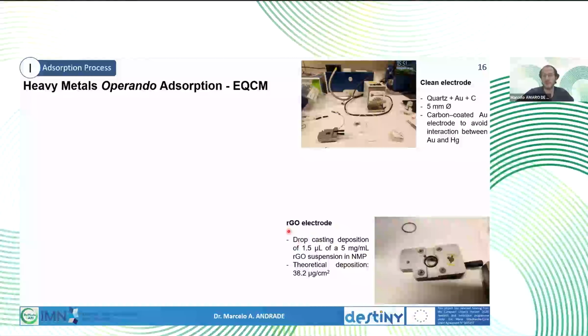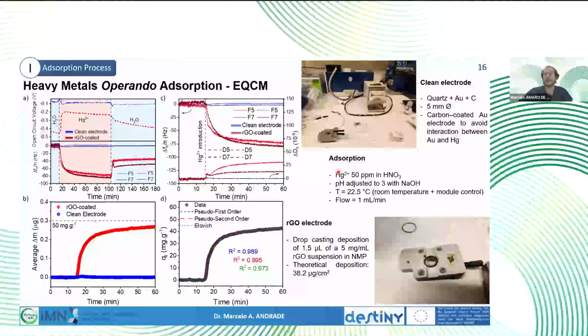So I cast this quartz with reduced graphene oxide and made a flowing solution of mercury 2 plus at 50 ppm in nitric acid pass over it. The pH was controlled, the temperature and concentration of mercury, and there was a constant flow of 1 milliliter per minute of mercury. You can see here on the first graph, first I was flowing water, so we do not see a frequency change. That is frequency over here. I was tracking OCV also while doing that. And then once the mercury solution reaches the RGO, we see a very pronounced drop in frequency, which correlates to an increase in mass of this quartz. So we see the adsorption curve happening. The RGO mass is increasing as mercury is flowing.